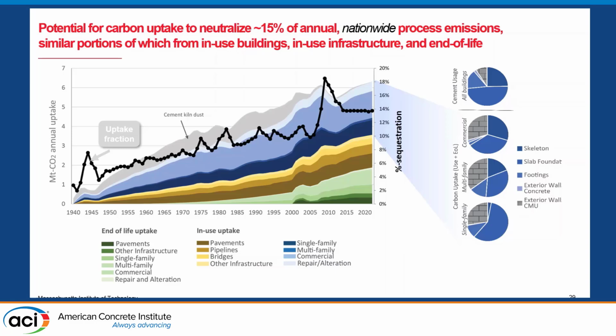But the largest percentage comes from the in-use uptake of buildings. And the interesting thing about buildings, which other examples will reiterate, is that although a small fraction of the cement usage goes to the concrete masonry units in the exterior wall and the basement wall, a significantly disproportionately larger portion of the carbon uptake occurs in these elements.